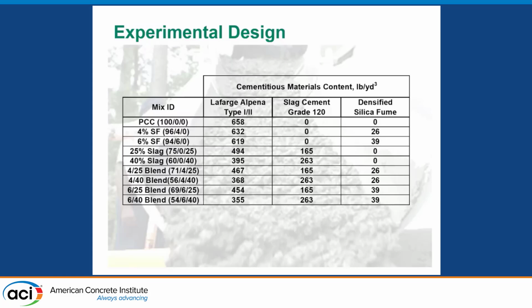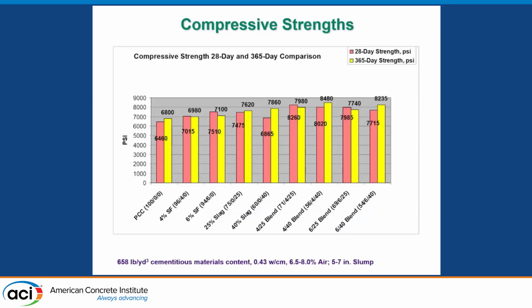So you can see that there is a reduction in Portland cement. Unfortunately, the calculators today don't calculate CO2 savings very well, but by just going to a 25% blend, it's about a 20% reduction in CO2. And I would believe that if we could make this an even lesser cementitious mix by using the silica fume, it would probably be reduced even further.